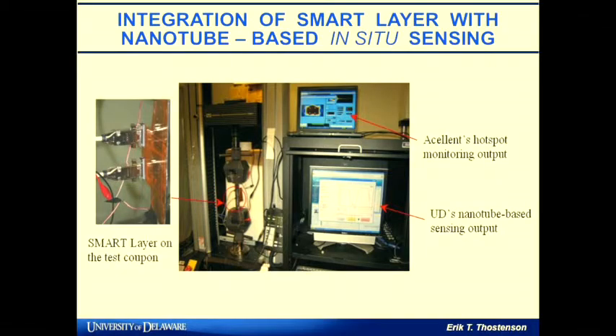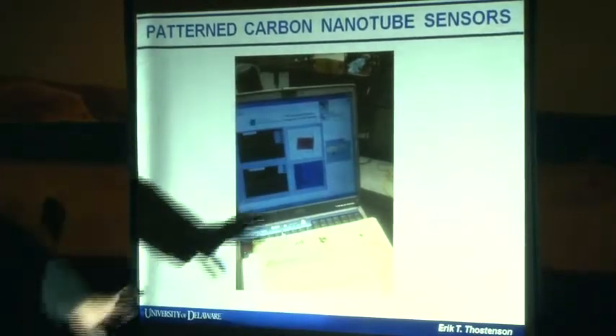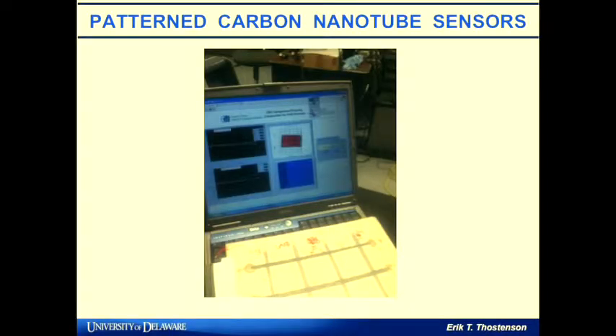In phase two we more integrated the systems looking at damage. With just four electrodes we're able to localize the normalized electrical response, seen in the C-scanned image. We've also patterned carbon nanotubes in orthogonal layers as a composite sensor. In a real-time demonstration, you can see a finger pushing on the panel and the panel bending, as well as bending at the back corner — these distributed sensors in the composite respond in real time to deformation. We take it to outreach events and museums where people love to grab, shake, and twist it.